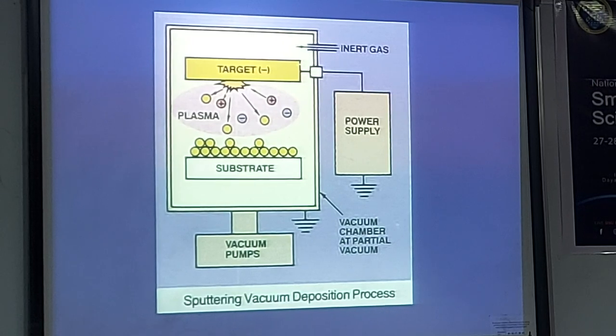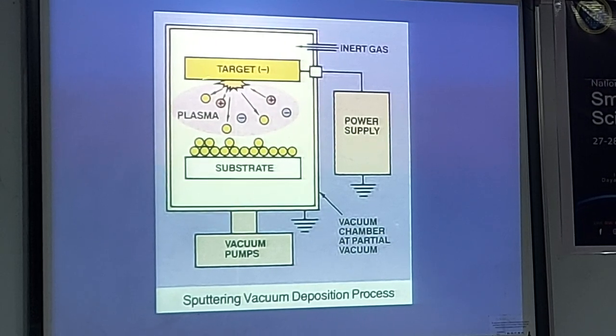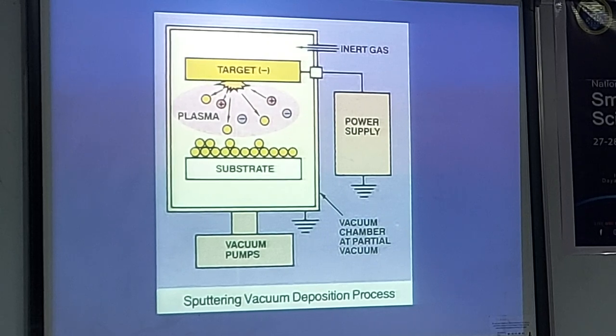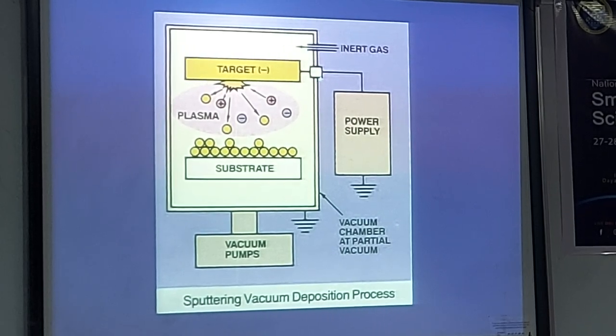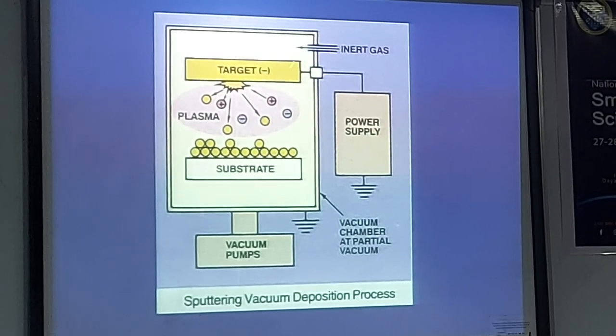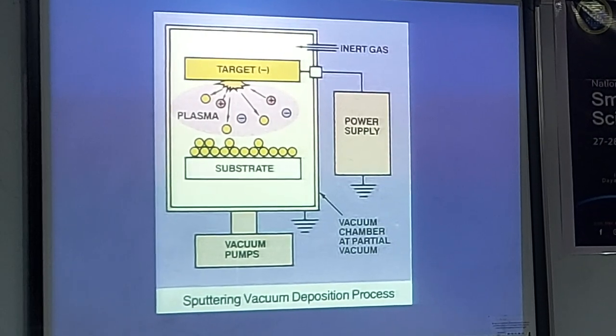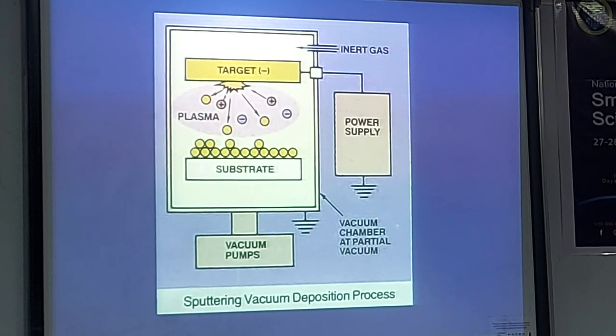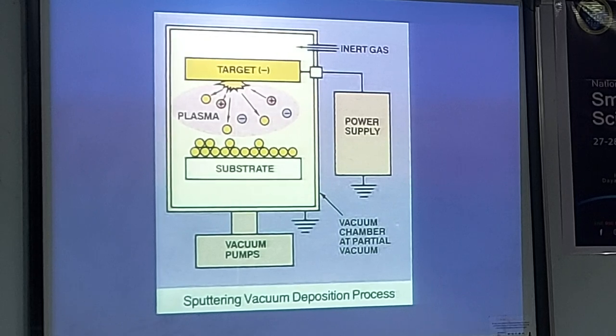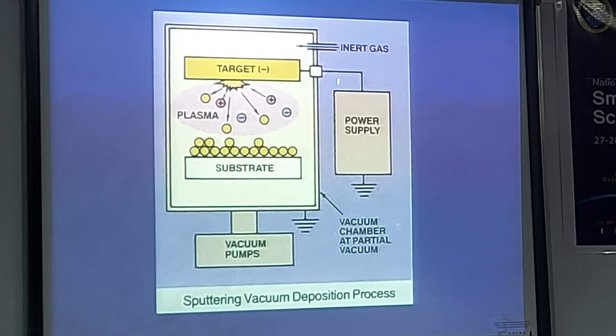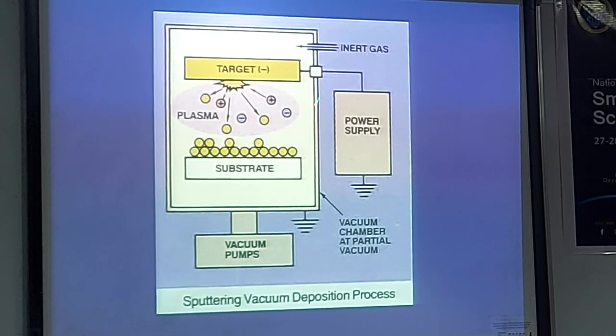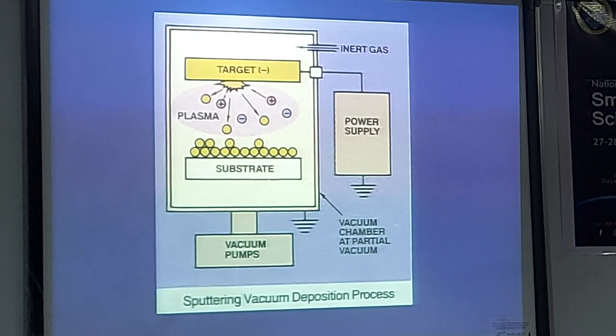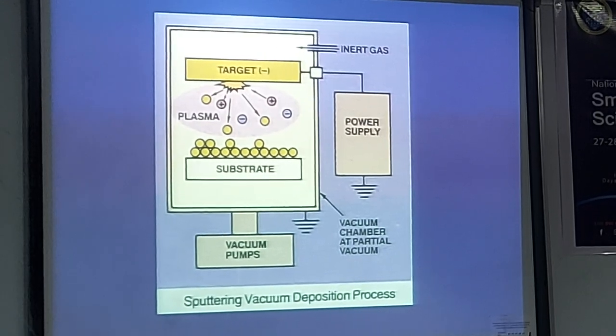If you use a third electrode in order to improve the adhesion process and the deposition rate, it is called triode sputtering. Most of the metals can be deposited by the DC sputtering technique. But if you want to deposit insulating material, the versatile technique is RF sputtering, where we use a radio frequency supply. I will not go into the details of this, but this is a simple schematic to show how the sputtering process takes place.